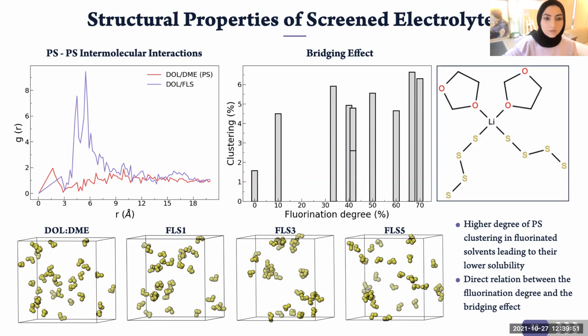We also see that with the fluorinated solvents, if we look at the x-axis here, which indicates the degree of fluorination, there is a much higher probability for the formation of a bridging effect, where a lithium is coordinating more than one polysulfide species at a time, compared to the unfluorinated electrolyte, where there is a much lower probability of this bridging effect forming. So because the competition to coordinate with the lithium cation in fluorinated solvent is lower compared to that in the conventional electrolyte, this leaves room for the anions and the polysulfide species to coordinate with the cation, leading to more contact ion pairs and clustering effect, which eventually leads to the reduced polysulfide solubility in these electrolytes.